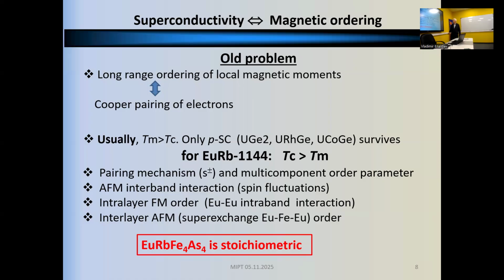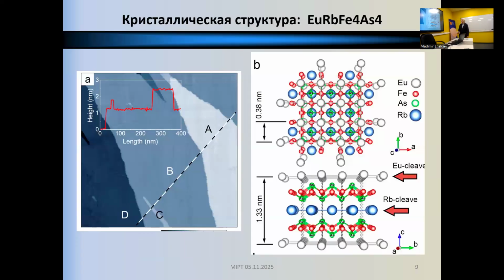So we have quite a complex picture of intralayer ferromagnetic order, where europium atoms have a strong ferromagnetic order in the intralayer, and an interlayer antiferromagnetic structure. And I wish to stress that this is a stoichiometric material, therefore it makes for a very interesting and fruitful study of materials with no doping effects, no impurity effects.